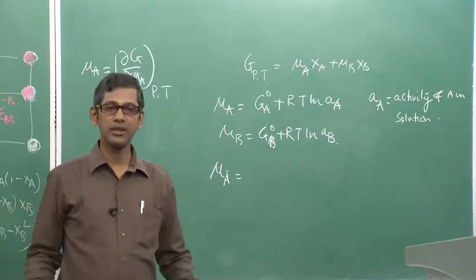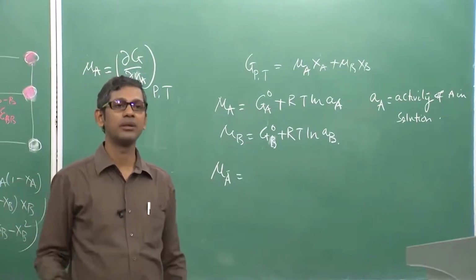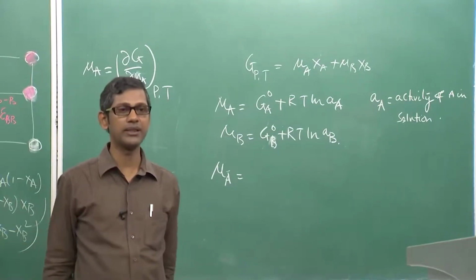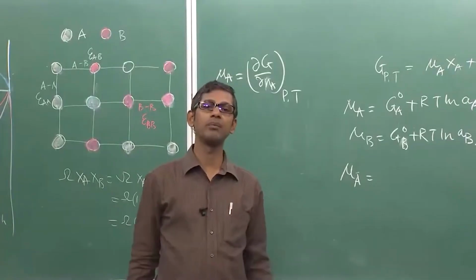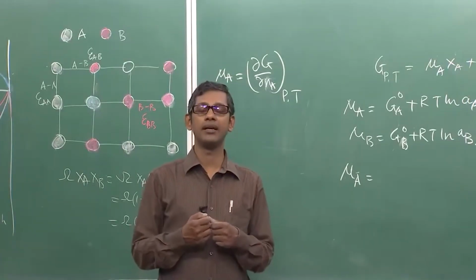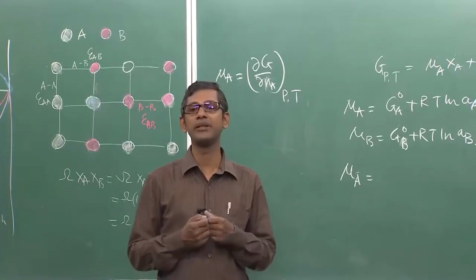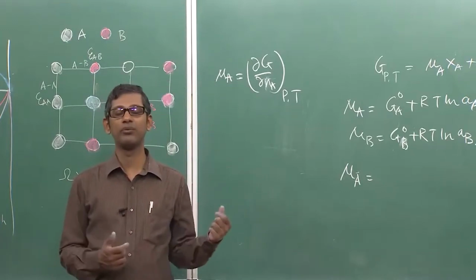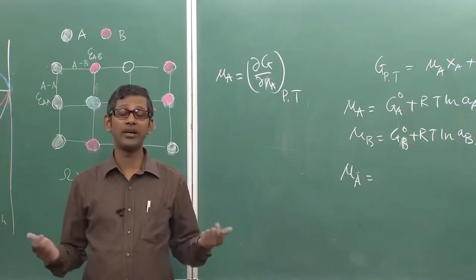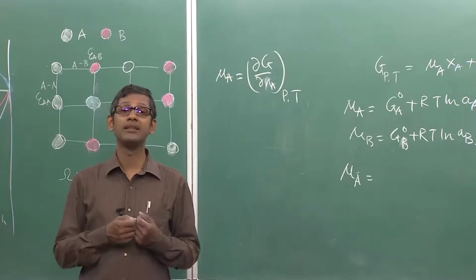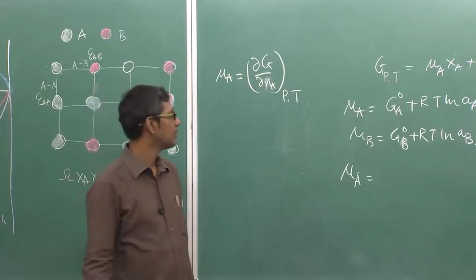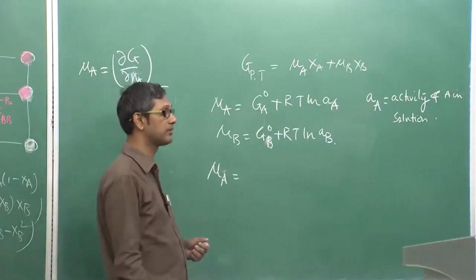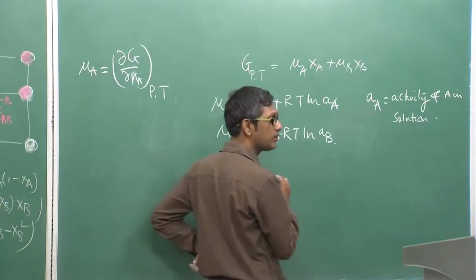And we know Raoult's law tells you that in a liquid solution activity is equal to mole fraction when it is very dilute or very concentrated. Okay, for A reagent and B reagent I can always apply Raoult's law, but only in those limits. When you prepare liquid solutions with concentrations in the middle of the XB or XA values like 0.4, 0.5, 0.6, 0.7 or even 0.8 or 0.3 of XB, deviations from Raoult's law are observed. So that is why you need to know the actual expression of the chemical potentials as a function of mole fractions, and it seems these are related to gamma.